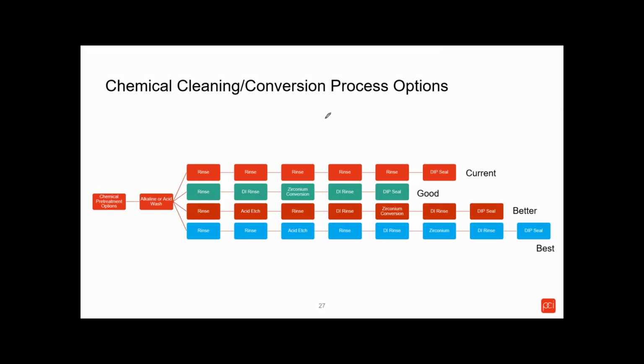As we said, your performance affects process steps. So here we're just looking at the cleaning and conversion process, what's often referred to as pretreatment. We have several options here, and it depends upon which method. The current one would use an acid wash. That's why I would say acid or alkaline, but the first one we're showing here is acid. You would acid wash it. Why would you use acid? Because the substrate's aluminum, you need to etch the aluminum oxide off that surface. And then you follow it with a rinse. In this case, they had multiple rinses in their current operation. And then the dried-in-place sealer would be applied at the very end to improve its corrosion performance and the adhesion of the substrate to the powder coating. So that's the current method.